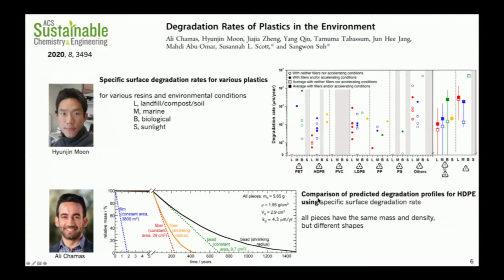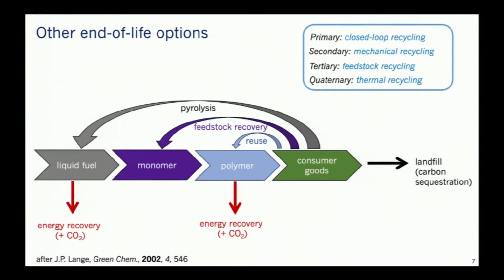And so the surface area is a very important parameter here, perhaps even more important than the actual chemical composition of the polymer. And so if we take a piece of polyethylene with different surface areas and make different assumptions about how the surface area changes as the polymer degrades, you can come up with lifetimes that vary from a couple of years to a millennium or more. So it's a very, very challenging problem to get your head around and to get good data on to study these kinds of issues. So degradation in the environment, even for polymers that are considered fairly degradable, can be very, very slow.